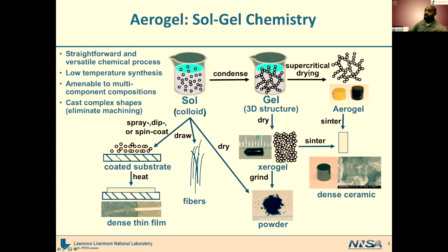Or if we actually want to maintain that porosity, because we want to use that for the final application, you can do something called supercritical drying. The way supercritical drying works is that you would take that liquid, heat it and raise the pressure to take it into the supercritical regime. So it's no longer a liquid or a gas. It's a new regime called a supercritical fluid. And you can then follow that within the phase diagram. Once you're in the supercritical regime, you're no longer a liquid or a gas, you're supercritical.